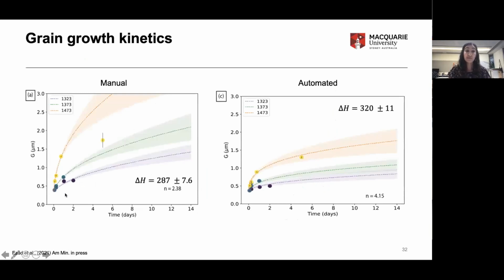What I found was that between manual and automated techniques, the important number, the grain growth exponent n, was markedly different. For manual techniques, a grain growth exponent of 2.3 meant that we could expect interface limited grain growth, whereas for a grain growth exponent of 4, we were talking about a completely different diffusive mechanism. I don't have time today to go into all of the grain growth kinetic mechanisms, but they are detailed in the paper for those of you that are interested.